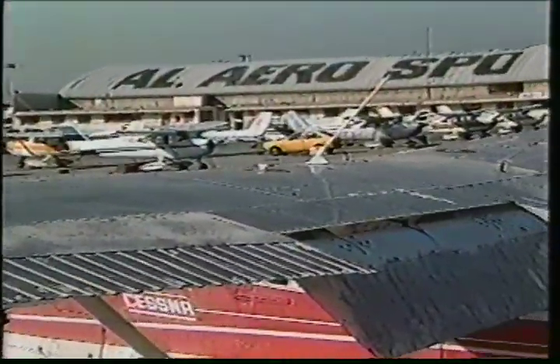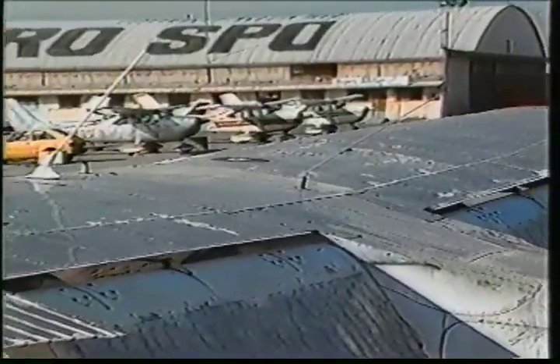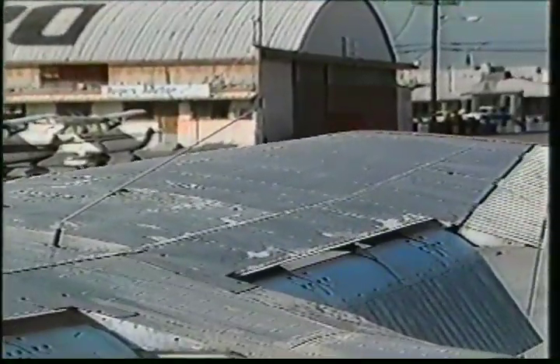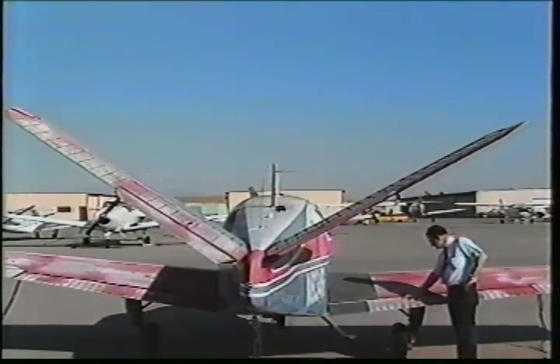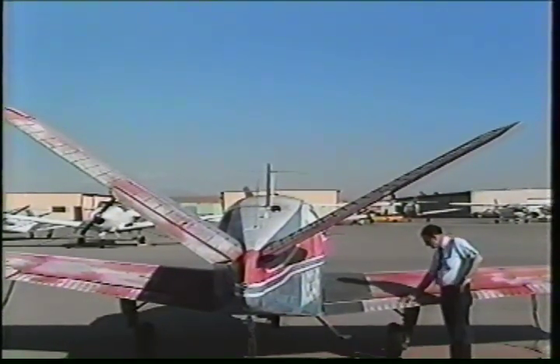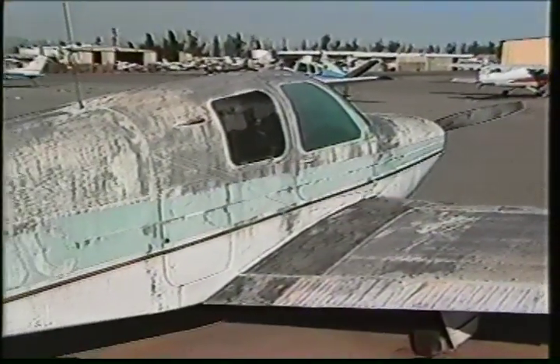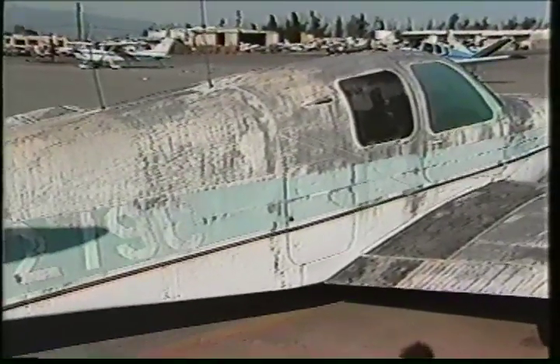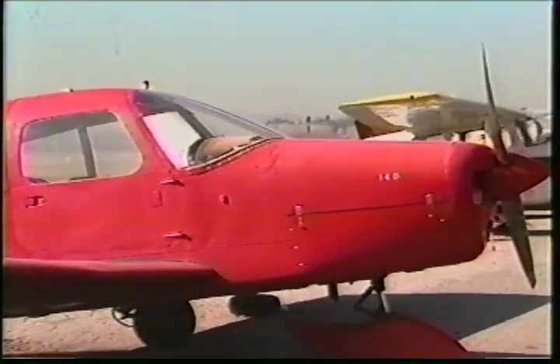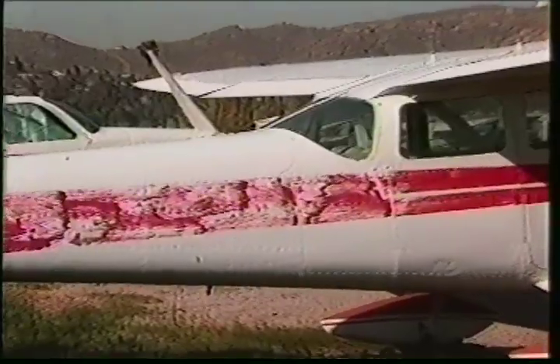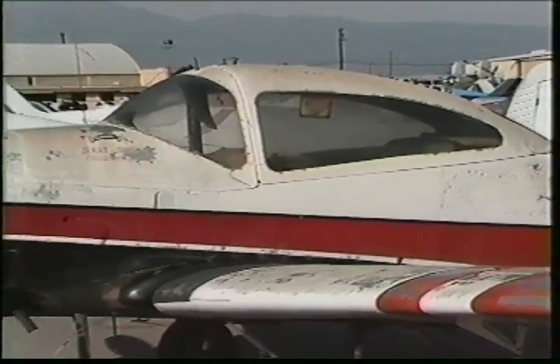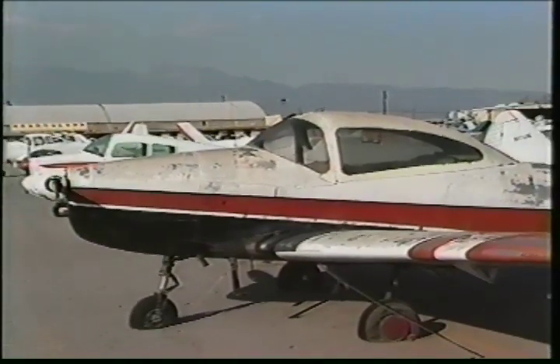As for the durability of finishes, there's no finish that will match the unlimited service life of properly protected polyester fabric. Even the best brands of the most durable type of metal finishes on metal aircraft stored outside in the southwestern sun in adverse weather start to lose their gloss in about 8 years. The high-gloss, fast-drying, brittle acrylic-based polyurethanes developed for the automotive repainting market and widely used to paint metal aircraft and, unfortunately, many fabric aircraft start to deteriorate and become dull in about 3 years when exposed to the sun and weather. It is common knowledge in the paint industry that epoxy finishes are about as durable as synthetic enamel. After about 2 years exposure, they start to chalk.